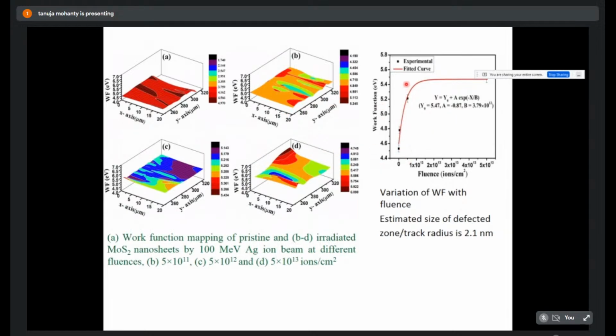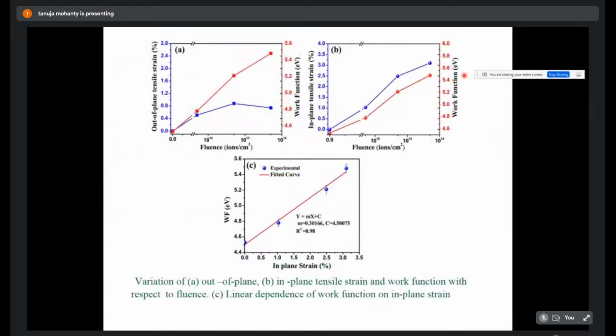So that gives a work function variation here. If out of plane tensile strain and you have the work function here, the out of plane tensile strain goes like this, but your in plane tensile strain and this one goes very parallel to each other, so they are linearly proportional to each other. So this work shows how we can prove that the strain in the material affects the work function of the material.